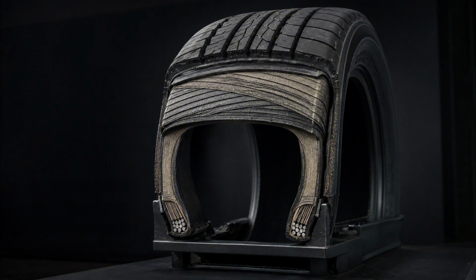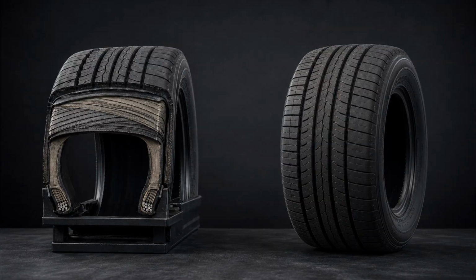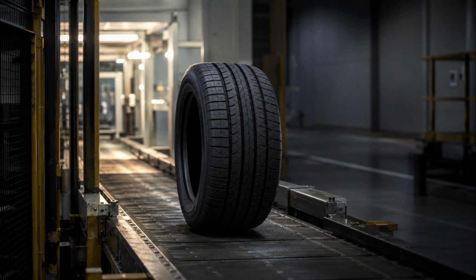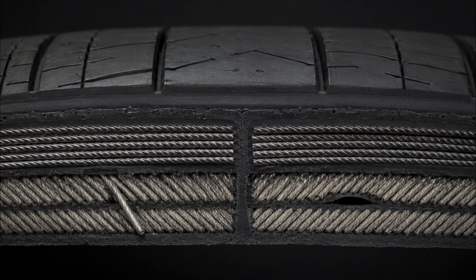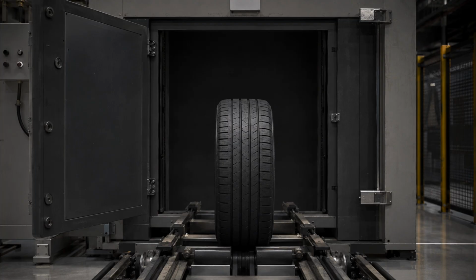When the cycle ends, the press opens. The tread is sharply defined. The sidewall carries permanent lettering. The soft green tire has become an elastic pressure vessel capable of supporting load and surviving repeated deformation. A cutaway reveals the result. The inner liner forms the smooth internal surface. Textile cords pass through the casing. Steel bead bundles sit inside the lower sidewalls. Steel belts reinforce the crown, and the tread covers the structure that stabilizes it. The layers have not become one uniform substance. They have become one working system.